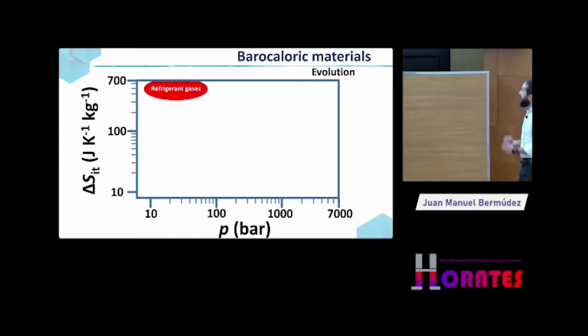And the target will be that of the refrigerant gases. So refrigerant gases are around 500 joules per Kelvin per kilogram, okay, under pressures below 60 bar, which is the maximum for the CO2, but normally they're going to be between 10 and 20, okay? So the first materials that were studied for barocaloric purposes, the solid state materials, were metallic alloys. As you can imagine, to compress a metal is going to be very hard, so to try a solid phase transition in a metal is going to be really hard. So they needed to apply really, really large pressures, over 1,000 bar, okay, which is far from the commercial needs. And the entropy change was also quite far from the refrigerant gases.